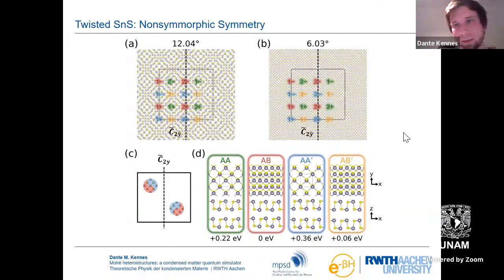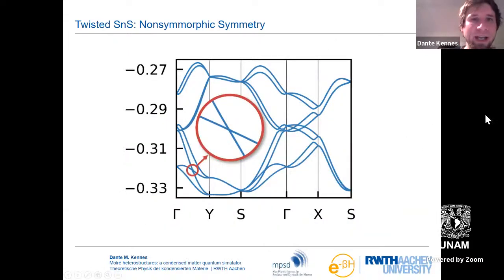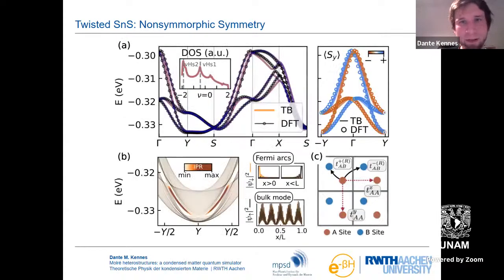And what this leads to, and of course the first step is to characterize this by DFT, is flat bands. So you see these bands here are very flat, but the non-symmorphic symmetry now protects so-called hourglass fermions here at this particular point, which is in between the high symmetry points of gamma and Y. There's a whole theory of non-symmorphic symmetries and how that leads to protected hourglass points. The important thing to note is that this is a material suggestion to actually engineer these things in a condensed matter platform, which is very rare.